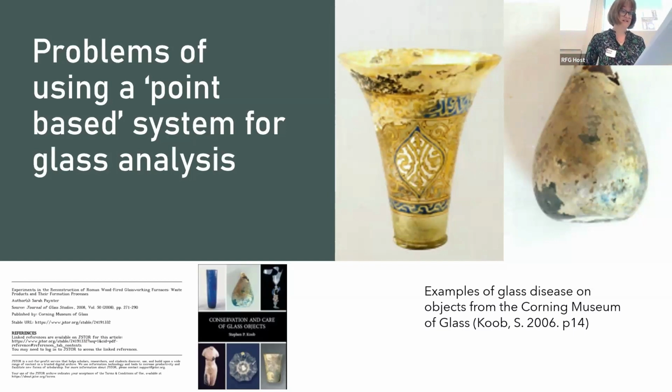The process of manufacturing Romano-British glass, as is the case with all manufacturing really, no matter how much we want to think about it, can be fraught with errors. And as outlined by Sarah Painter, Mark Taylor, and David Hill, this manufacturing method can also lead to the slumping of vessels and the pooling of colorants in the necks or other curved portions of the vessels, which can lead to weaknesses. This pooling of minerals, as well as the large inclusions picked up during the firing and cooling processes, not only causes problems with the structural integrity of the vessels, but also when conducting material analysis from the vessels.